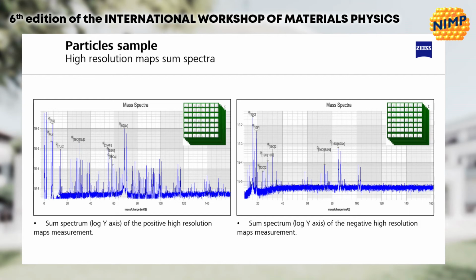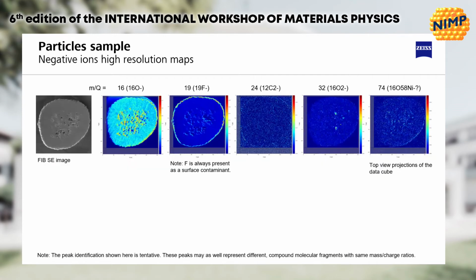And what we create by scanning with the gallium FIB, synchronized with the mass spectrometer, is a mass spectrum at every single point. In the end, you have a library of the full mass spectrum over the full surface. We did the same for negative ions, also with a library of the full area. And finally, we started to correlate.